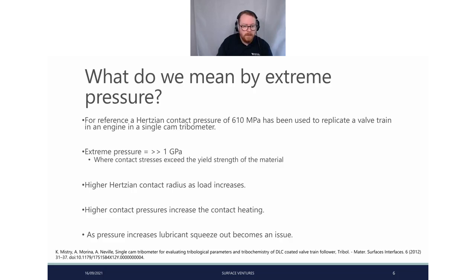Okay, and then by extreme pressure, what do we mean? For reference, I have this single cam tribometer paper down here. For that, a contact pressure of 610 megapascals was used, and this was used to replicate a valve train in an engine. But for extreme pressure, typically this is over 1 gigapascal, if not much greater. This is where the contact stress exceeds the yield strength of the material, or can. And of course, with this, we will get a higher Hertzian contact radius as the load increases. With higher contact pressures, we can increase the contact heating. Once again, that's going to drive that dynamic